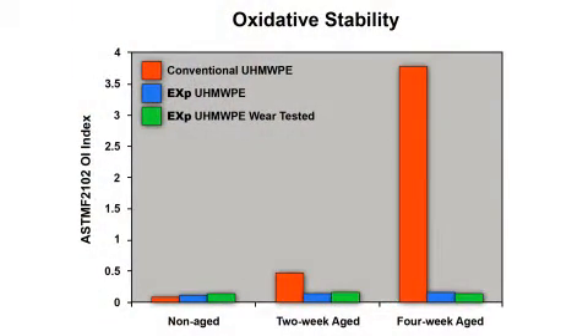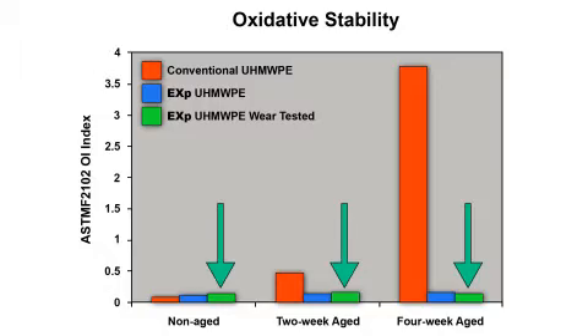We also did a second test to evaluate the oxidative stability by looking at material that had been through a very long, 5 million cycle wear test. So again, after 5 million cycles of wear testing, we looked at the level of oxidation in the materials, and we found that the vitamin E containing materials had negligible oxidation at the bearing surface. So again, this gives us some degree of confidence that the material won't oxidize in vivo.